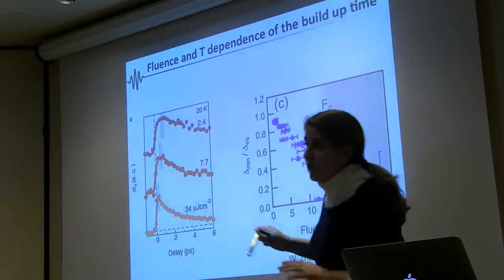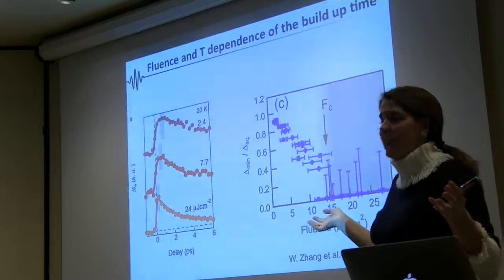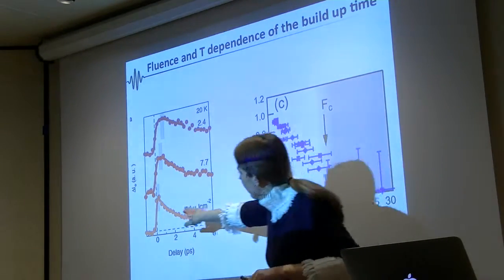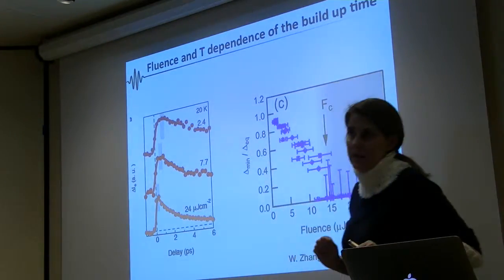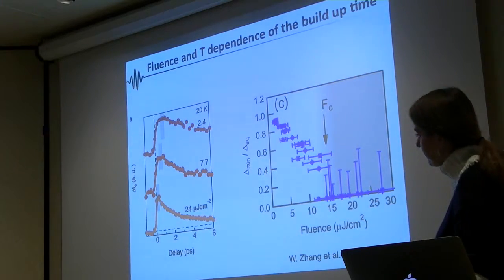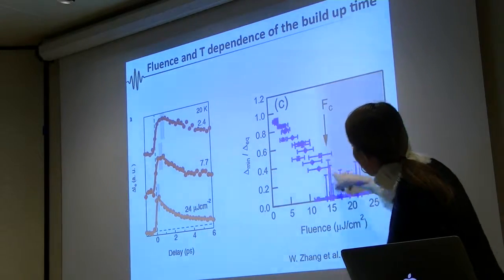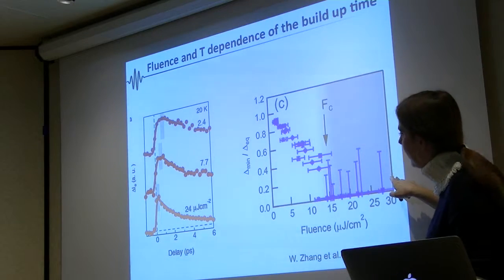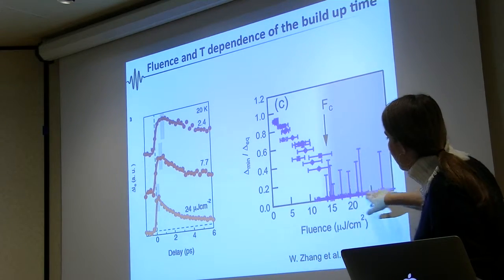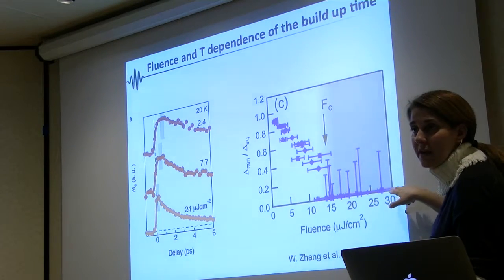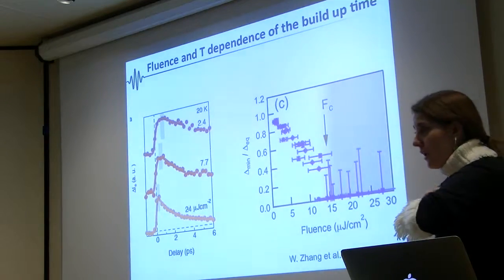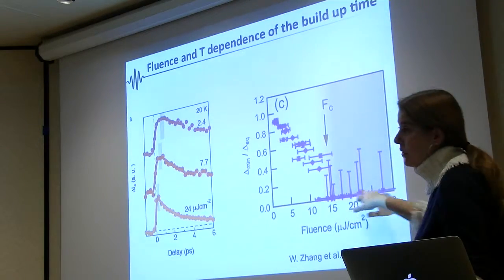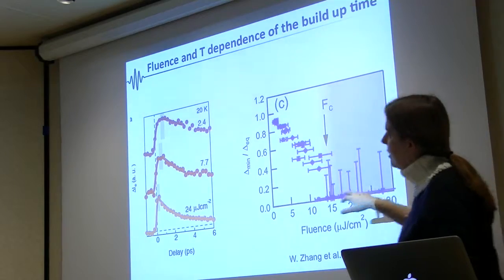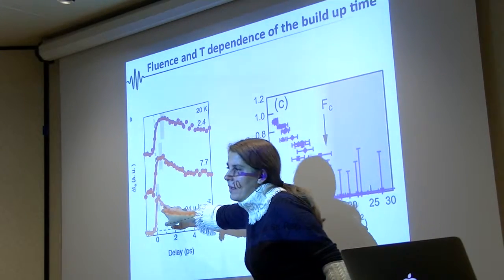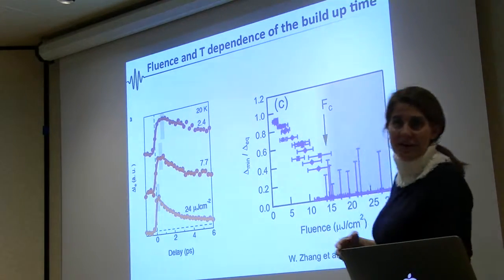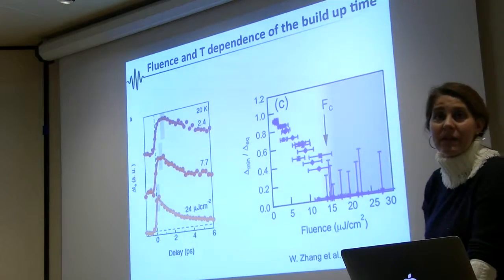But if you go to a fluence where I pretty much killed everything right away, at this fluence, then the response is immediate. So what we learn from here, and we can compare with what we learned from the superconducting gap, is that every time the energy I'm delivering to the system is big enough to kill all Cooper pairs, this is what is happening here, then my system responds right away, as we are observing in many metals we are studying. The response is right away, immediate.